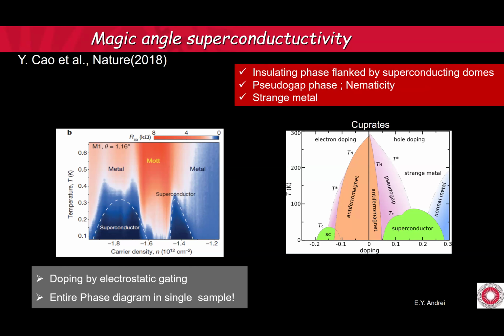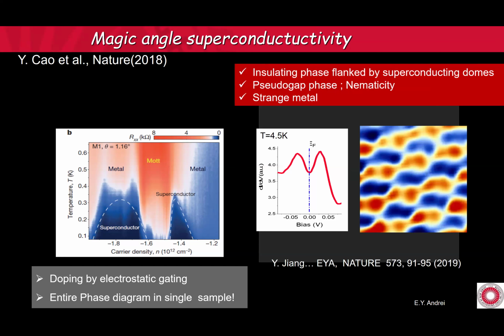So, an insulating phase flanked by superconducting domes, we have a pseudogap phase that we saw with STM, which happens above here. We have a nematic phase also in this regime, and people have seen strange metal behavior, the linear in T resistivity. So there's many signatures that resemble high temperature superconductors.